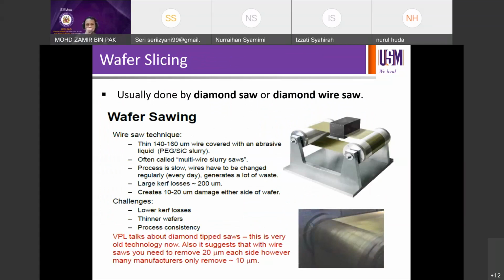So we use physical sawing, right? The diamond blade, a hard blade. On the other hand, you can also use a wire saw, but made of diamond, so it's equally strong to cut the wafers into pieces. For example, wafer sawing using a wire saw. This is particular to the solar industry as an example. For you to cut, say, 140 to 160 micron